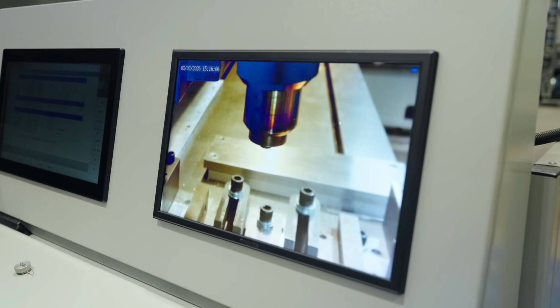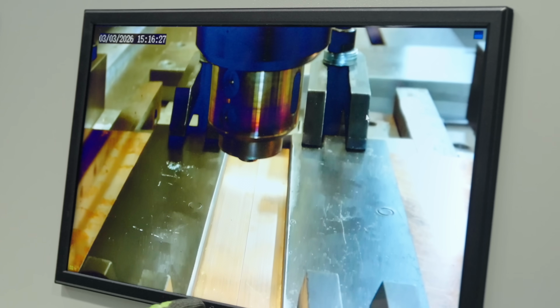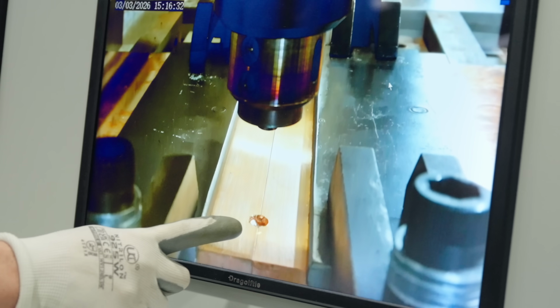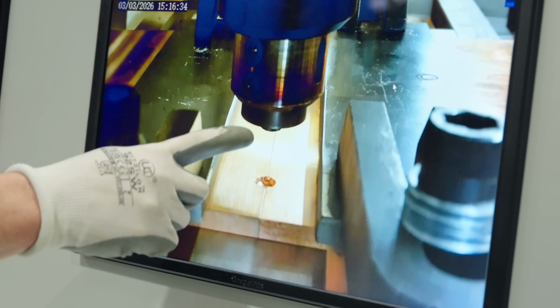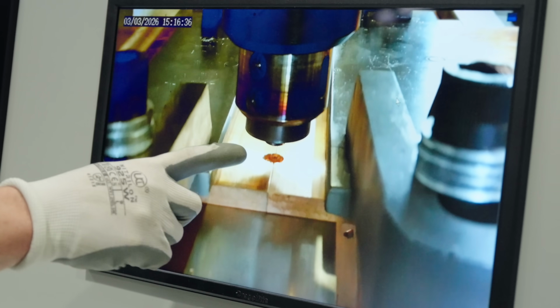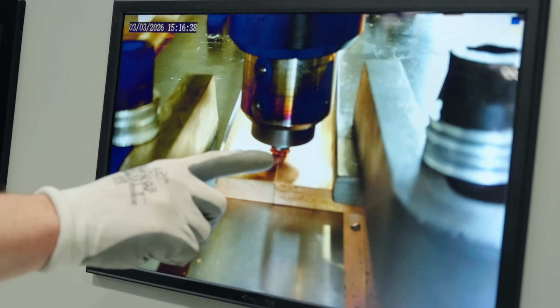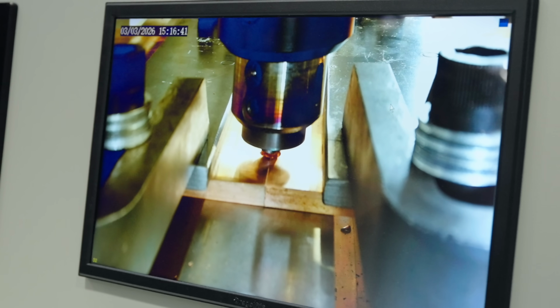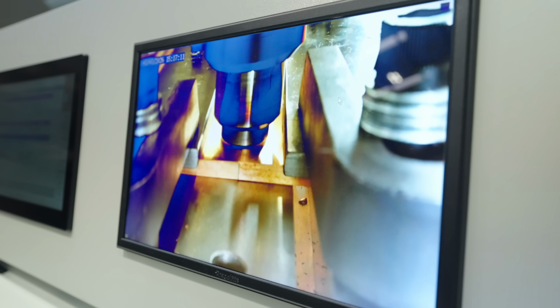So we're in our set position, coming down to our reference point. There's the seam. Now we have a little start hole there. So it's just to relieve the material to make sure that we get this shoulder down to the top of the material. And that hole doesn't go the whole way through. Right, we ready to go? I'm ready. Okay, so this is that slow down feed you were talking about, the 20 millimeters a minute.